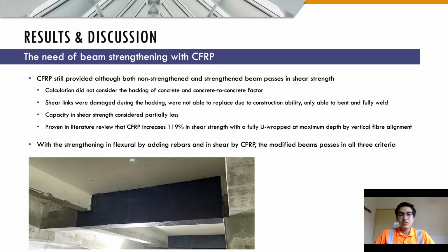It is proven in the literature review that CFRP increases shear strength by 119% with a fully U-wrap at maximum depth by vertical fiber alignment, which is exactly the same method applied in the actual modification work as shown in the figure below. With this, it can be concluded that with strengthening in flexural by adding rebars and in shear by externally bonded CFRP, the modified beams pass in all three criteria. It is also learned that when a certain beam depth is reduced, a strengthening approach in flexural and shear strength is required.